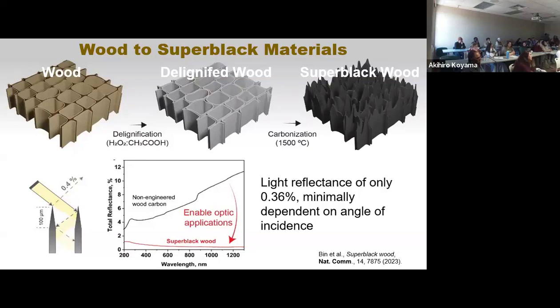If you take a look at the total reflectance versus the light wavelength for typical non-engineered wood carbon, then this is the value, high reflectance. It's black, but not black enough. And we wanted to have something that really absorbs all light, nothing escapes. And then the value of that reflectance with this wood material that you see in the top right, in the black color here, is a material that is special. It's called super black. And super black exists.